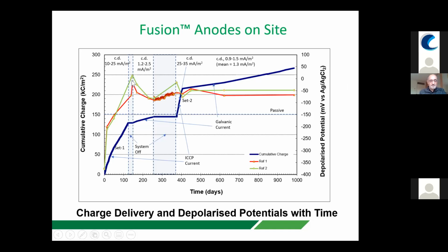Even after we allowed them to depolarize a little bit, over this period, the potentials always maintained a passive potential. It didn't really matter that we applied the extra amount of charge in this case. The steel was passive anyway, and it just remained passive. So the passivation really was achieved by that very early initial charge.